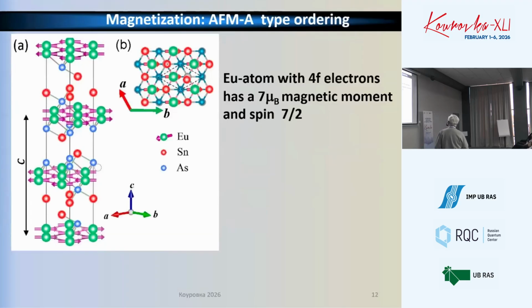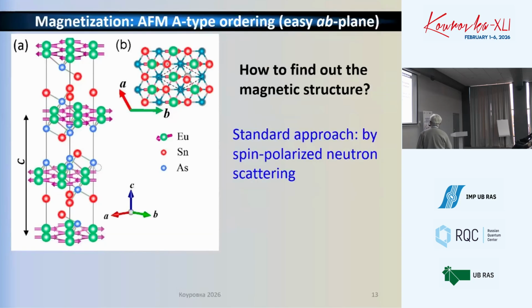Now, what about the magnetism? The europium atoms have 4f electrons, which are responsible for magnetism, with a 7 Bohr magneton magnetic moment and spin 7/2, and this is the source of the magnetic ordering. Now, an interesting question might be addressed to young researchers: how to find out the magnetic structure. By magnetic structure, I mean both the order and the direction of the magnetic moments. So for several years, people discussed whether the magnetic moments of europium are directed either perpendicular to the plane or in plane.